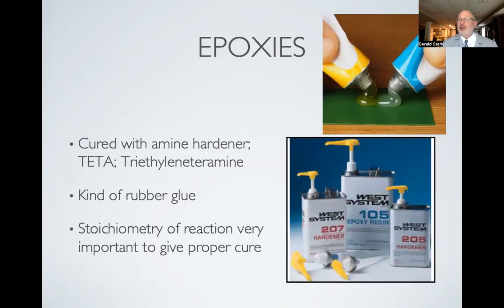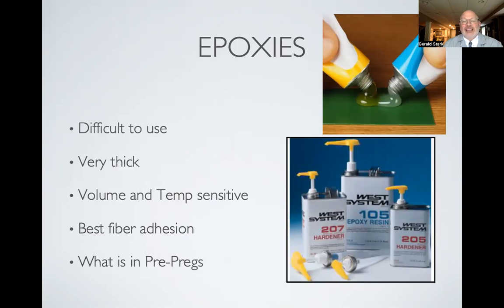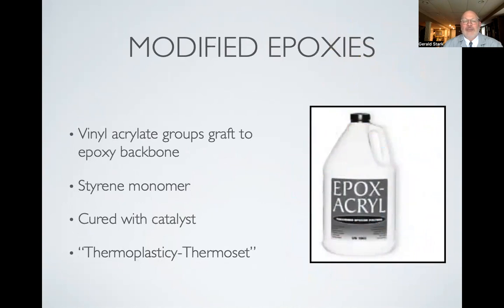Epoxy is a form of rubber glue in a sense. It was cured with triethylenetetramine, and this was also somewhat dangerous if the stoichiometry or the mixture was not predicted accurately. It was fairly thick, so we tried to water it down with acrylics. And so that's when we got into the modified epoxies, which were also cured with a catalyst. So it's a thermoplasticky thermoset, somewhere in the middle.